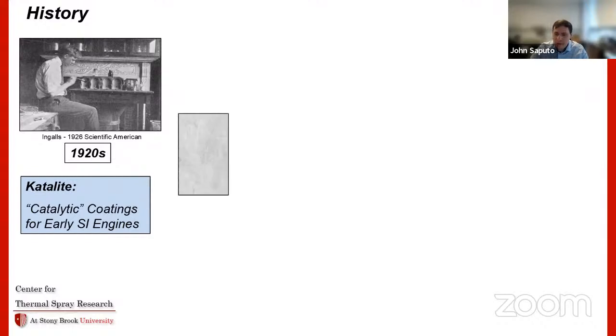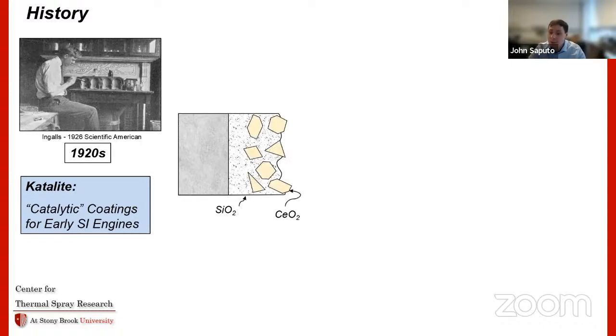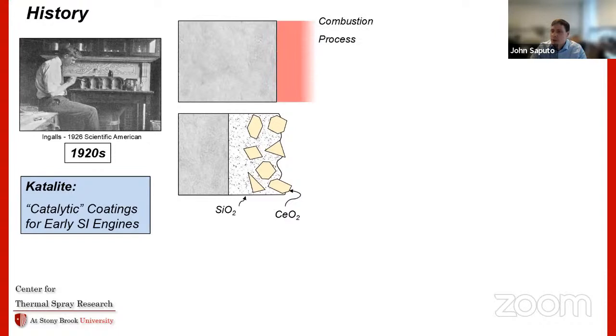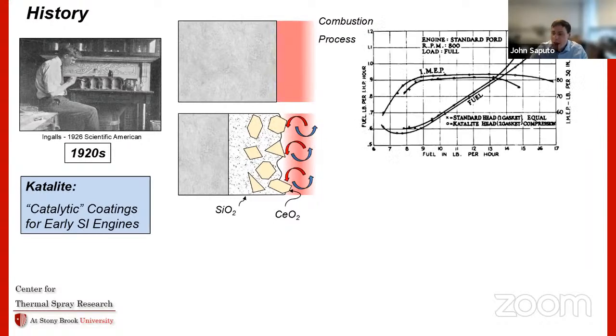And part of the idea was that you could have some wall material, you could apply silica, which is what he's painting on as a slurry coating there, and then put a layer of cerium oxide on the surface. So normally in an engine, you would have some combustion process and hot gas traveling over the surface. In this environment, they imagined that the hot gases would interact with the cerium oxide particles that are on the surface, have some catalytic reaction that would allow the combustion process to proceed to a fuller combustion.